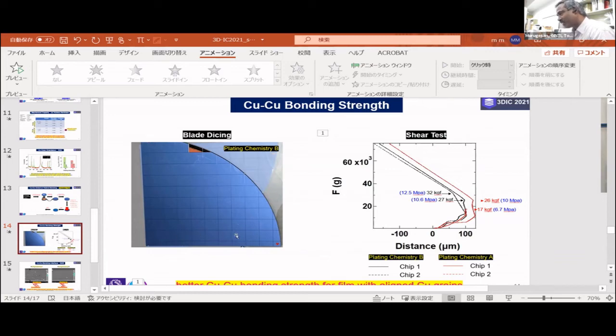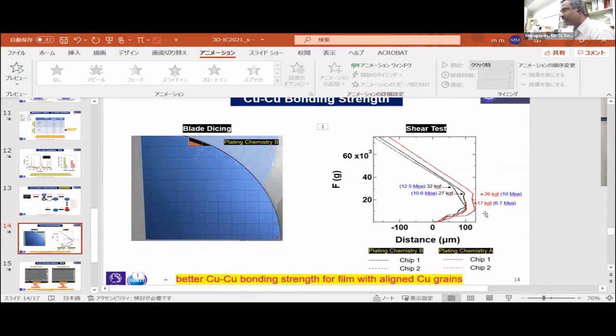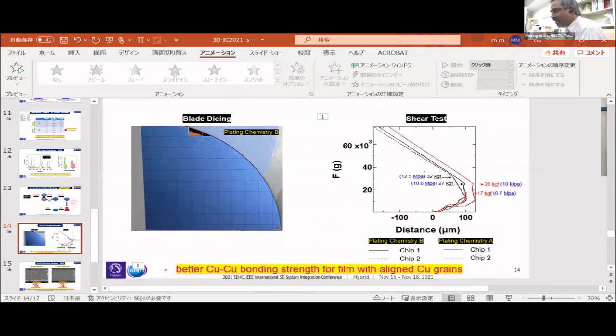And we took some of the chips and did a shear test. As you can see, the maximum bonding strength we found, the black one is for the new chemistry and the red one is for the conventional one. We did observe quite close bonding strength, if not a little bit higher value. So it shows that our bonding strength is also good, if not very good, it's comparable to the conventional.